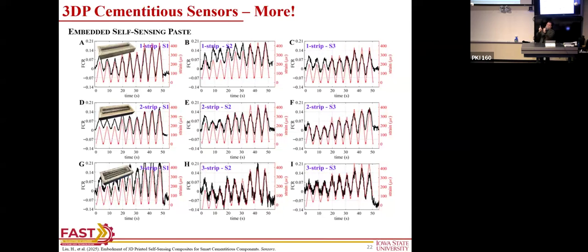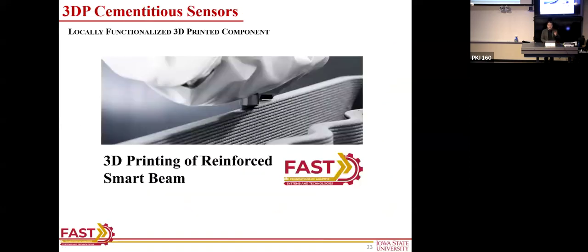These beams were very small. So now we try to go a little bit bigger and also more towards field applications, something that makes more sense. So we did what we call smart beams. Where the first layer, we have a layer that is conductive, a layer that is not. And you'll see in the video that we put reinforcement as well. Not just because we want to, just because we want to demonstrate that we can 3D print with reinforcement. And also, well, for testing, once you start cracking it, you don't want it to be destroyed.